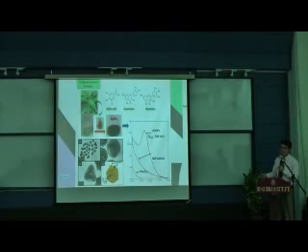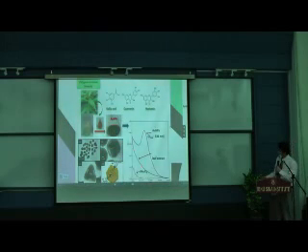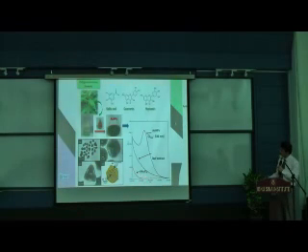This is Sohila. Actually, she has used kassoon leaf extract, which has gallic acid, quercetin, myricetin, flavonoids. Flavonoids are very well-known antioxidant compounds. So simply, you add a leaf extract to an aqueous solution of gold, and you get this colorful, stable gold nanoparticle. And this is the optical absorption of the gold ion and leaf extract, and then adding them together, you see the surface plasmon band showing gold nanoparticle formation.